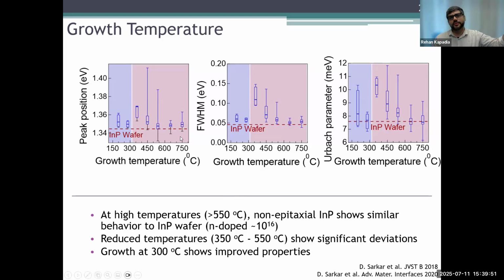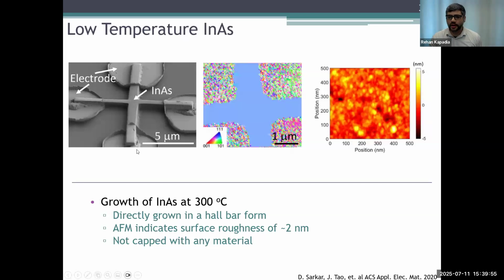So then we said, all right, what about indium arsenide? Indium arsenide is a high mobility material. Can we grow it on a non-epitaxial substrate, such as silicon dioxide, and then measure the mobility and see what we get out of it? This is just some pictures showing that we in fact did that. We turned it into a Hall bar. So we made a cross of thin film indium arsenide grown on a silicon dioxide substrate.